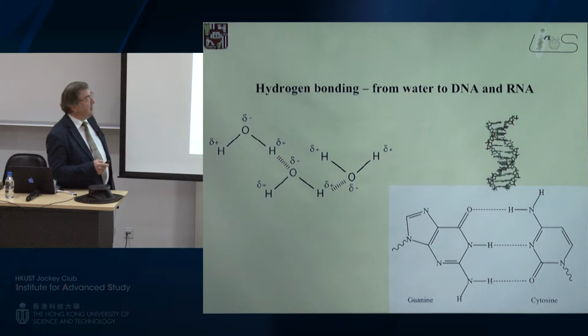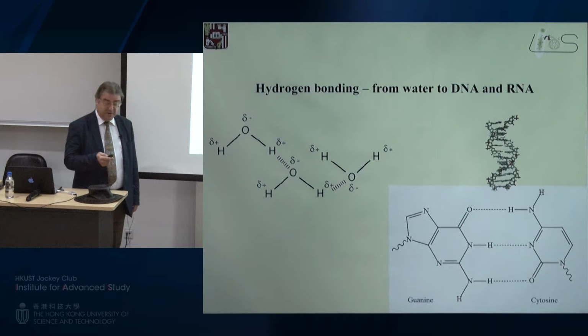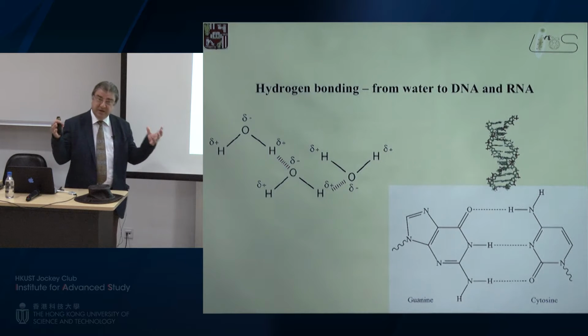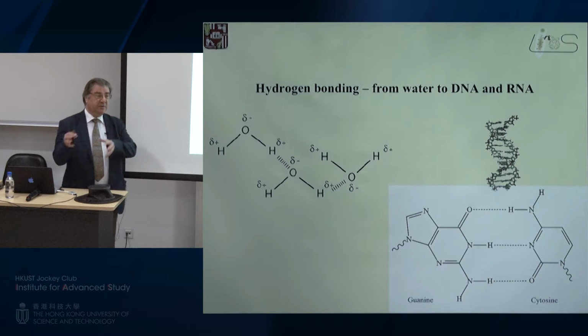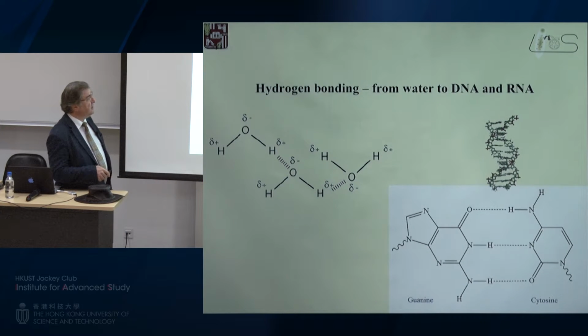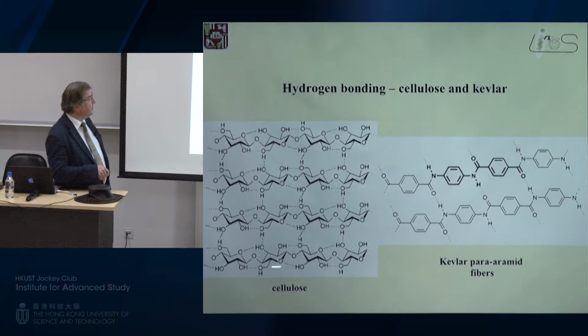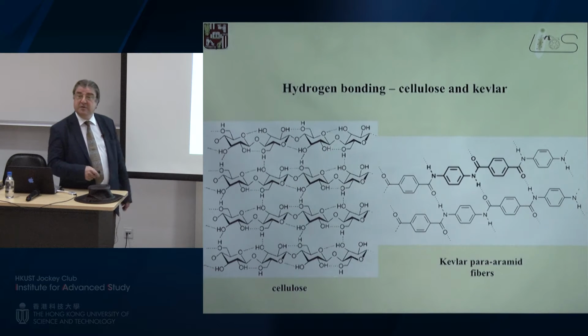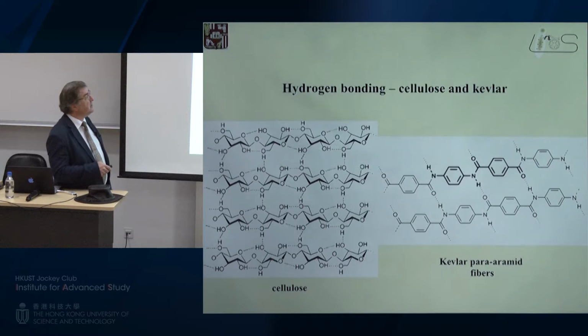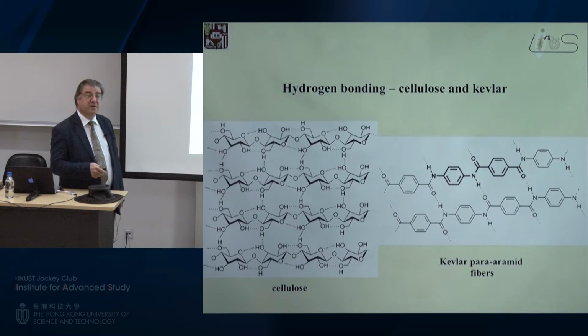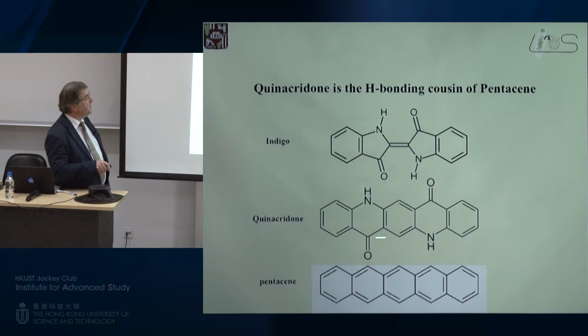Why is it so stable? Our assumption is that these hydrogen bonds play a big role in this kind of semiconductors, and therefore we gave the name to this family hydrogen bonded semiconductors, because I believe this is the general umbrella we have to look at. And indeed, that makes stable materials. We know from cellulose, for example, even the synthetic Kevlar fibers are based on hydrogen bonds, and it's a very stable material. People use this material for bulletproof clothes and helmets. So, this is, for example, quinacridone. This is my champion material. This is pentacene. As you see, very similar, just the hydrogen bonds are different. Therefore it's the indigoid family, but indigoids maybe you don't use, we call them hydrogen bonded semiconductors.